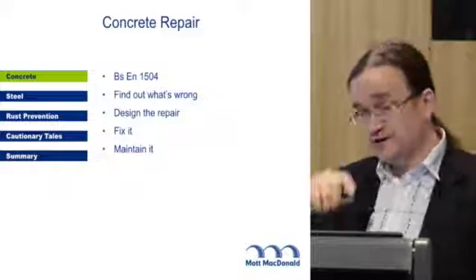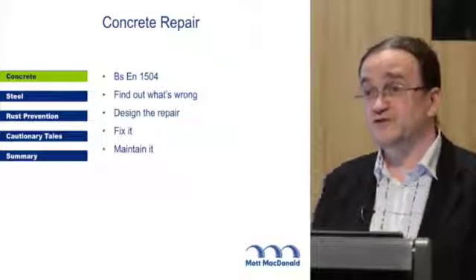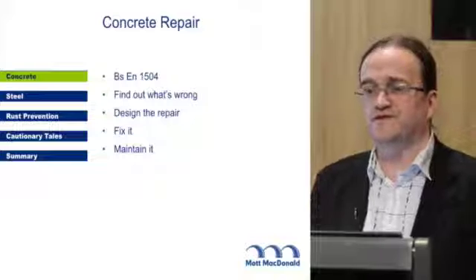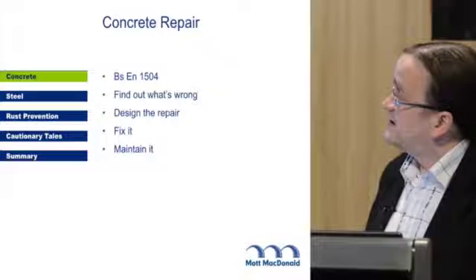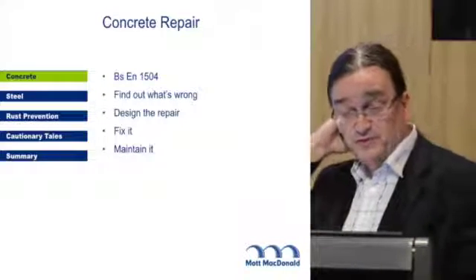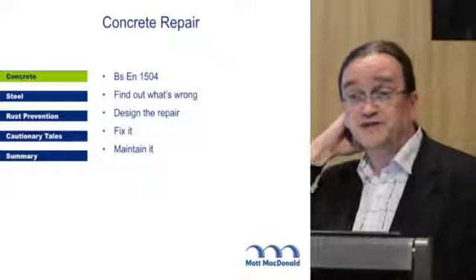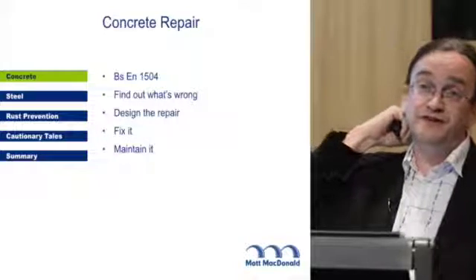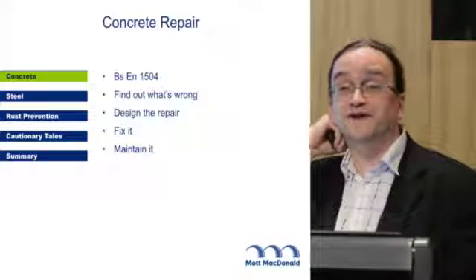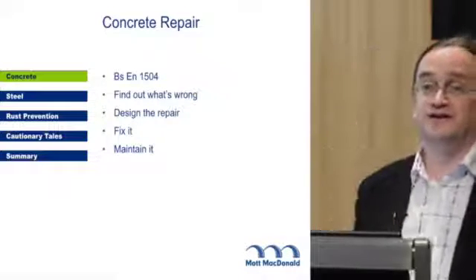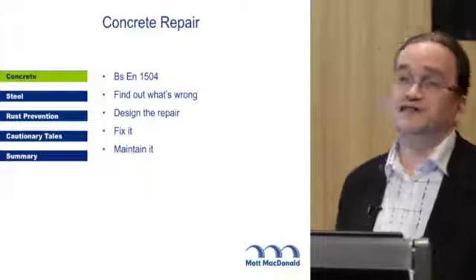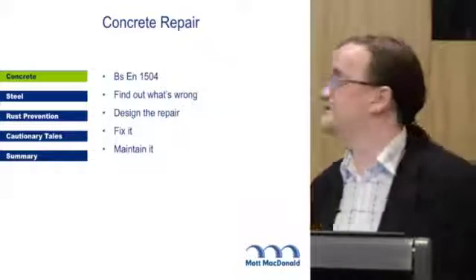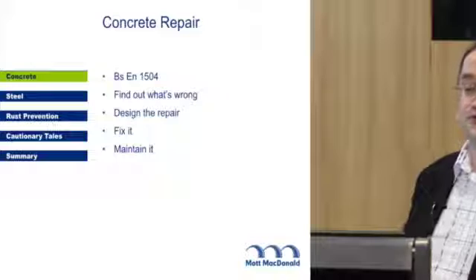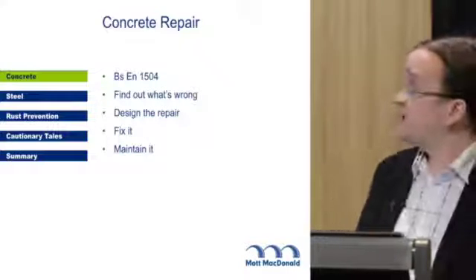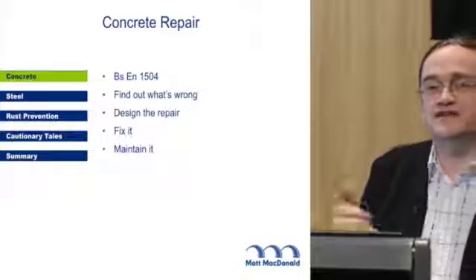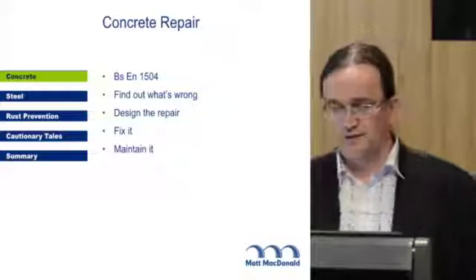It's called BSEN 1504, and it's come up with a radical suggestion that step 1 is find out what's wrong with your structure before you fix it. That was highlighted by a study that was done about 10 years ago that demonstrated 95% of the attempts to repair concrete fail within 3 years. Because rather than actually finding out what's wrong with it, we see a bit of concrete falling off, turn up with some stuff in a bucket and slap it on the hole. That doesn't work. So we now find out what's wrong, then we design the repair, then we fix it, and we keep records and we maintain it, because everything only has a finite life. Nothing will last forever.